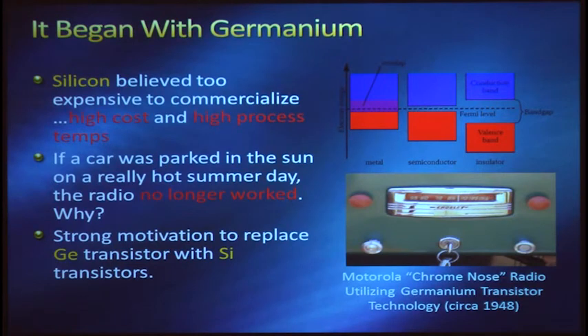So in the beginning, it wasn't a silicon-based industry. It was actually germanium-based, because silicon, even though it's derived from sand, was believed to be too expensive to commercialize. Very, very high costs associated with purifying silicon enough to make it electronics grade, and very high processing temperatures, about 1,000 degrees C.